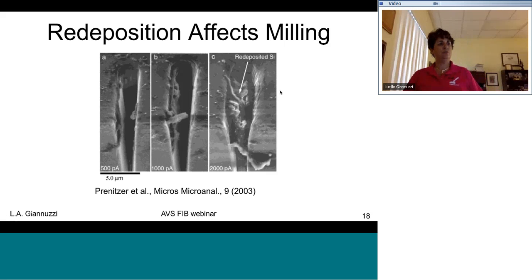And as I showed you earlier, depending upon how you scan the beam, the sputtered material will go to different places, resulting in redeposition. So the redeposition also affects what sort of milling artifacts you're going to get. If you try to mill the same pattern with 500 picoamps versus, for example, 2 nanoamps, the redeposition is going to be an issue at higher beam currents, and this is going to affect the quality of the shape. So if you're trying to mill something with a FIB, it's always, do I want to do it fast and sloppy, or do I want to do it slow but really neat? And those are sort of always the trade-offs that you have when you do FIB milling.